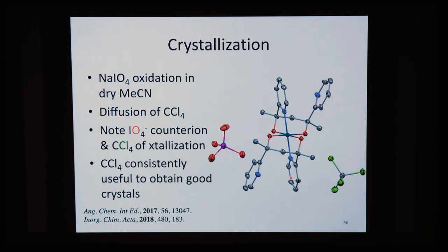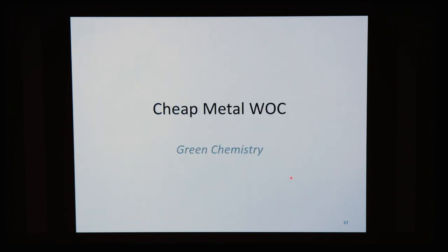And this is something that might be helpful in general. It turns out that carbon tetrachloride is useful in growing crystals. This material doesn't crystallize properly unless a tiny amount of carbon tetrachloride is present. And you notice also the periodate counterion as well. And this is not the only case where carbon tetrachloride has proved useful in obtaining good crystals.